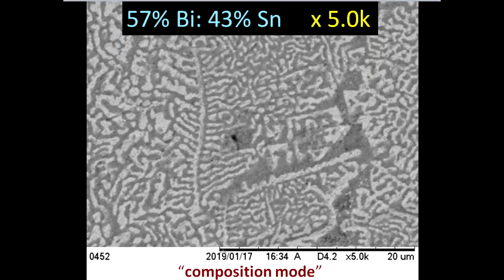And so the resolution down here, one of these little rectangles of dark you can see I'm highlighting, I'm going to say that's probably maybe 1/10 or 2/10 of one of these little boxes. That was 2,000, and a tenth of that is 200 nanometers. So we're really looking at the very small scale. If I could get in another factor of 10, I might be getting down almost to the atomic or molecular scale, but this particular electron microscope really can't get any better than that.